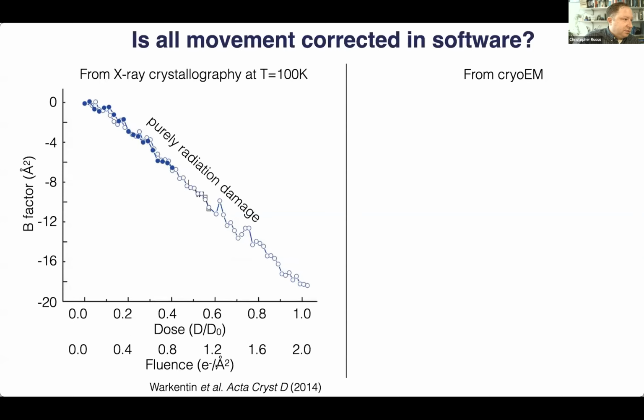So if you translate this to electrons per angstrom squared, even in the very first electron per angstrom squared, this should be perfectly linear in decay. And the mechanisms of radiation damage in X-ray are essentially the same as they are in the electron microscope. So this is what we would expect if there really was no movement.